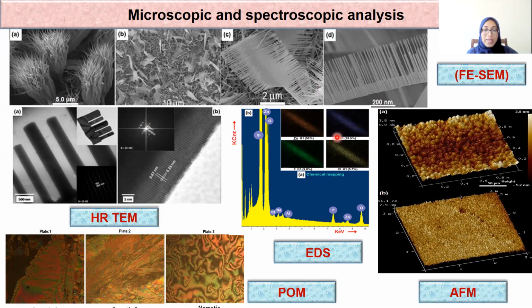Then the percentage of the elemental distribution of zinc oxide nanomaterial dispersed liquid crystal is demonstrated by the chemical mapping, as indicated here. This shows that the zinc occurs at a percentage of 56%, oxygen 28.5%, fluorine 9.8% and chlorine 5.7%. Chemical mapping offers an effective approach of exploring atomic level structure, chemical and functional information of